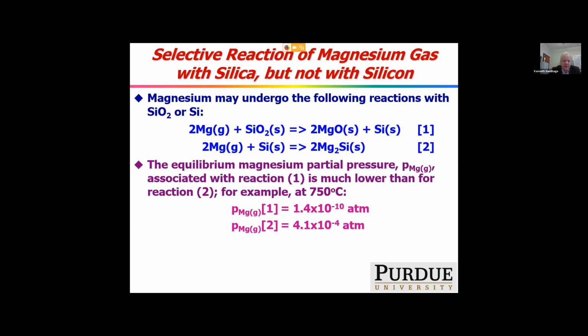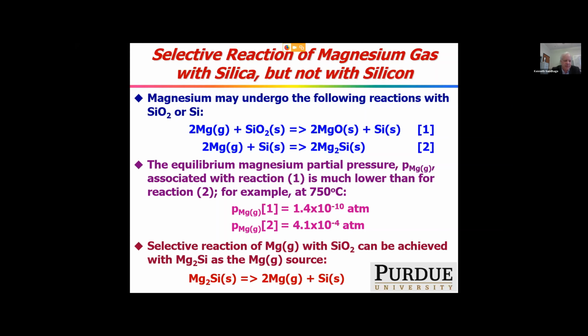So to get around that, we examine the partial pressures of magnesium required for both reactions to happen thermodynamically. So the top reaction is quite low, 1.4 times 10 to the minus 10 atmospheres. For the bottom reaction, it's quite a bit higher. So what that means is if you're below the 4.1 times 10 to the minus 4, but above 1.4 times 10 to the minus 10, you can get the top reaction to happen, but not the bottom one, reaction 2. A simple way to do this is to take magnesium silicide itself as the gas source.